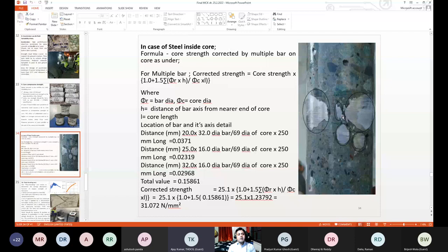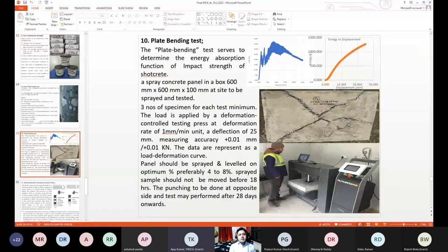Now this is the plate bending test. The plate bending test serves to determine the energy absorption function as impact strength of shotcrete. A spray concrete panel in a box 600 mm x 600 mm x 100 mm is to be spray tested. At least 3 specimens are to be tested. The load is applied by deformation control testing, pressed at a deformation rate of 1 mm per minute, until a deflection of 25 mm.